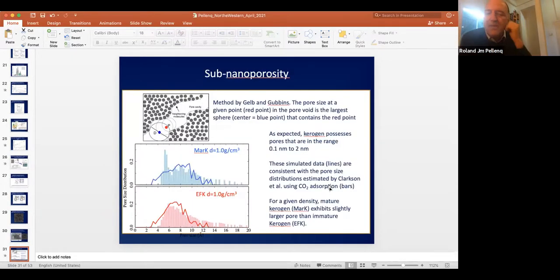Obviously, now we can be more quantitative and calculate the pore size distribution. So there are statistical ways to do it, basically inflating spheres in the pores. And when you start touching the atoms, then you collect the size and you do the histogram. So that will be the pore size distribution. And we do that for the different porous Kerogens.